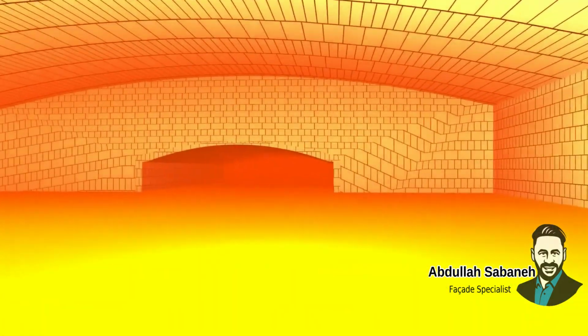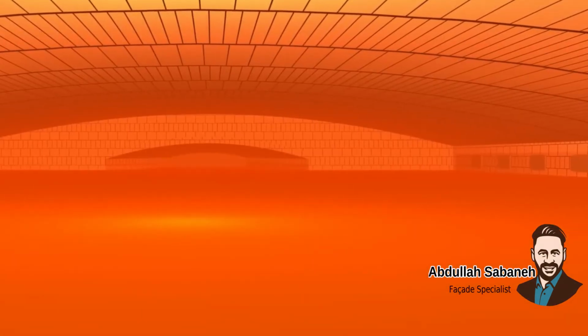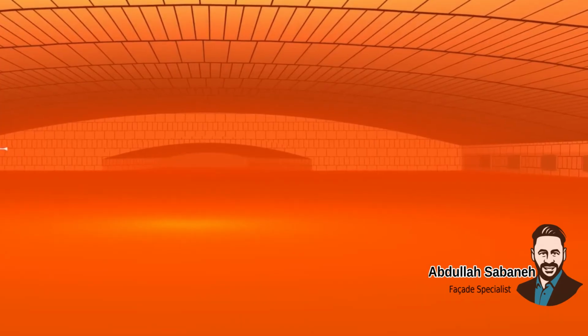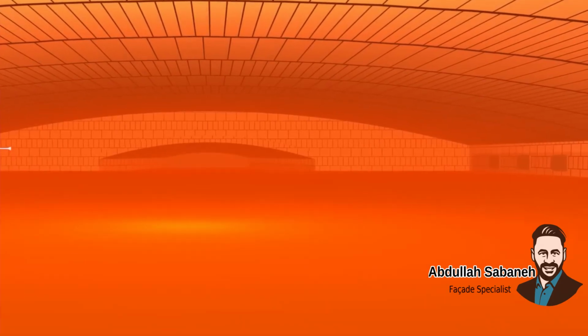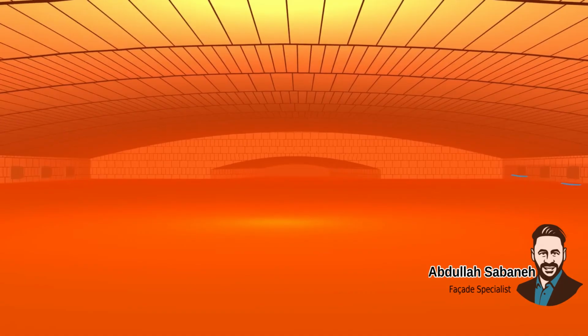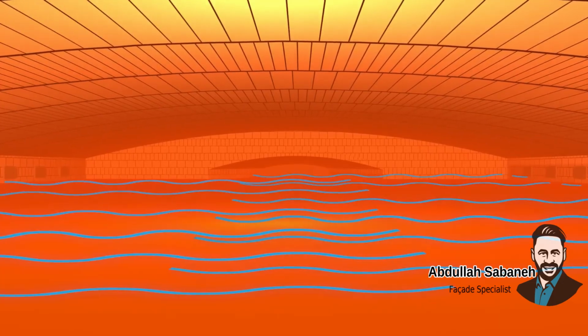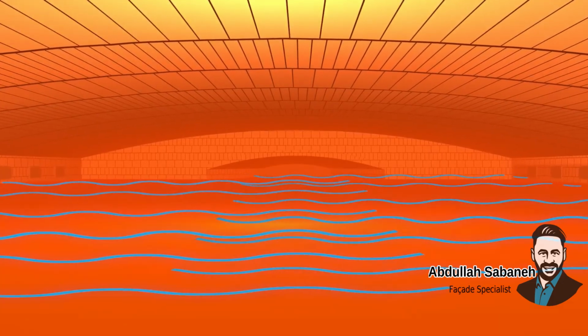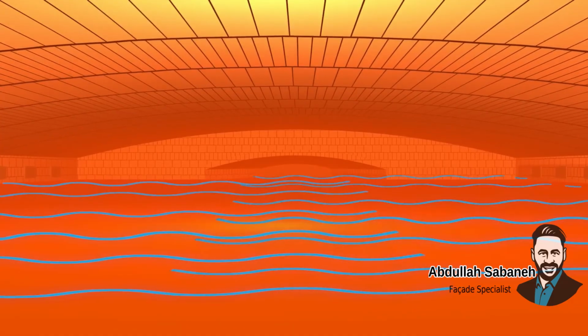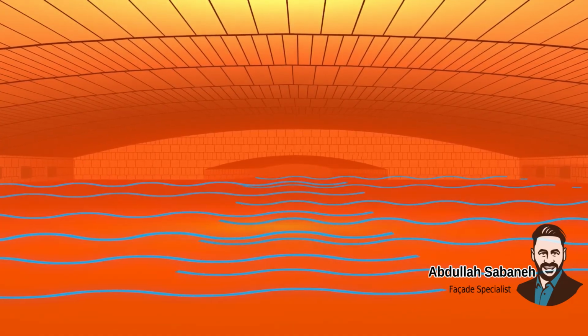In the working end zone, to prepare the spreading of the glass over the tin bath, it is cooled down from 1400 to 1100 degrees Celsius. A cold airflow is regulated for it to precisely reach the temperature and viscosity required at the forming zone.